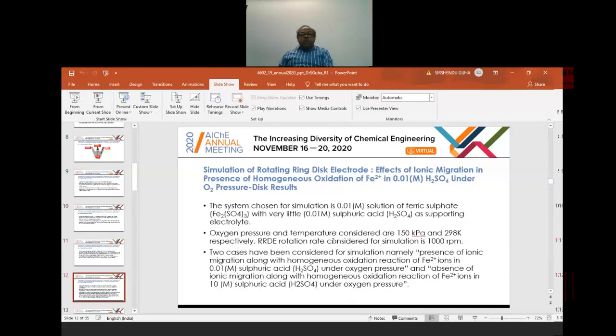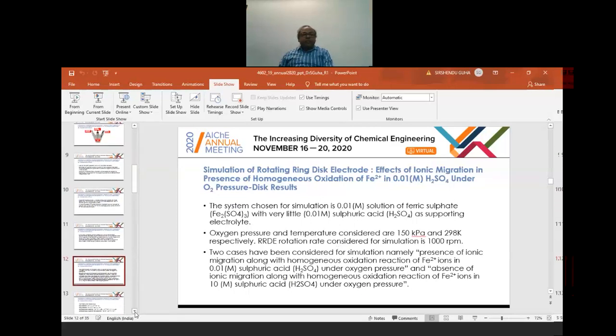Now, let me tell about the system I have considered for simulation. The system chosen for simulation is 0.01 molar solution of ferric sulfate with very little 0.01 molar sulfuric acid as supporting electrolyte. Oxygen pressure and temperature are considered as 150 kPa and 298 Kelvin, and the RRDE rotation rate is 1000 rpm. Two cases have been considered. One is presence of migration, and another is absence of migration.